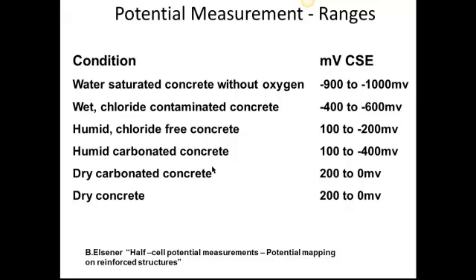Now, some more guidance. If you have saturated concrete, you can have very negative values which at the same time aren't actually corroding. So whenever you're forming opinions about the likelihood of corrosion, you need to be very aware of whether you've got wet or dry concrete, what season it is, and compare like to like. As I said, always look for the hot spots.